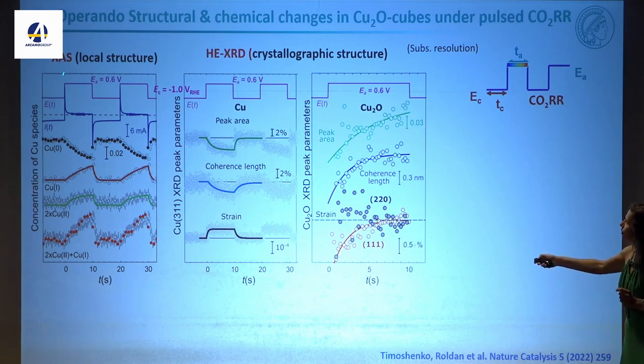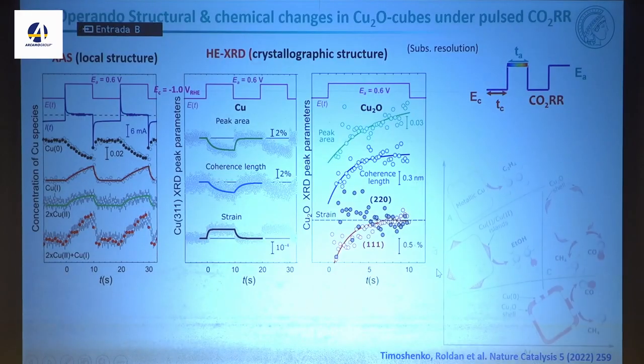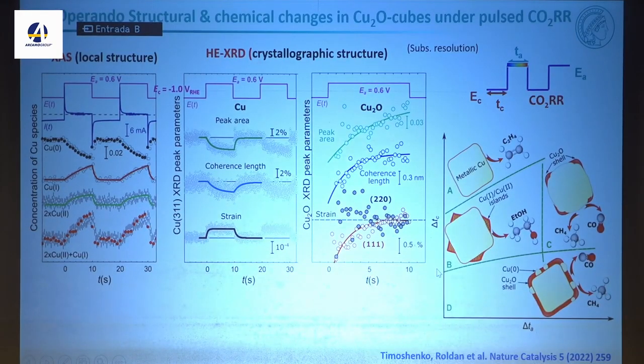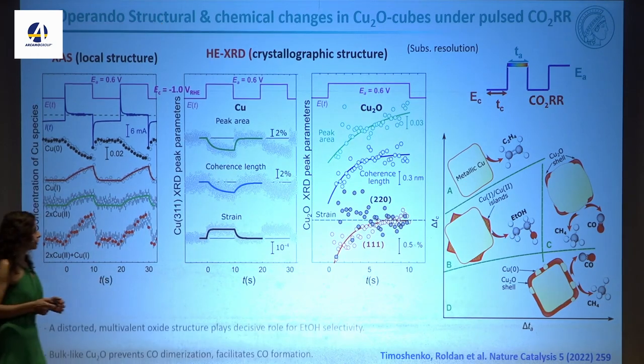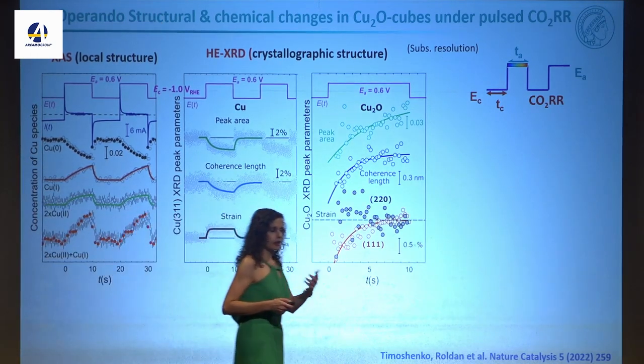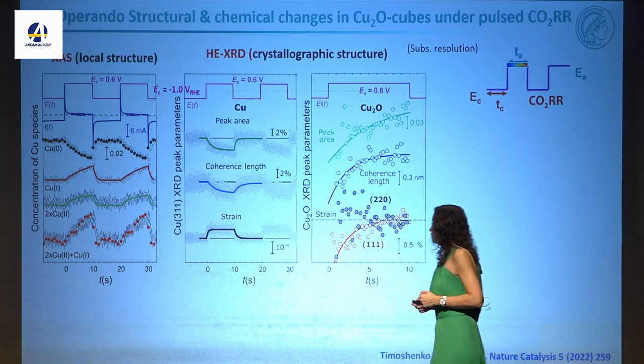And I can follow during these potential pulses how the activity changes. This is the current here. But I can see how the material oxidizes, copper 1 species, copper 2 plus species. Oxidation is slow during the applied pulse. Okay, it's not good. It's back, okay, sorry. So the oxidation is slow, and the reduction is very fast.